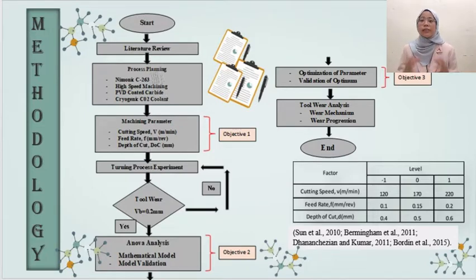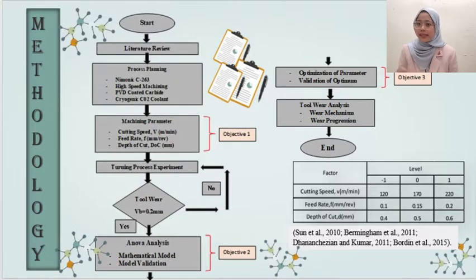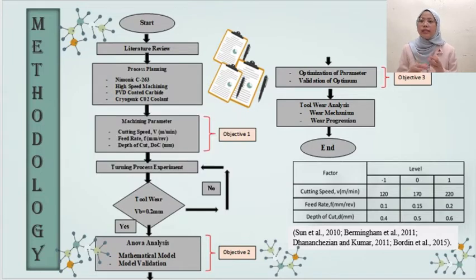Then, the research is planned using Nimonic C-263 with high-speed machining with the help of a PVD coated carbide insert, assisted by the cryogenic CO2 coolant. The cutting parameters like the cutting speed, feed rate, and depth of cut are selected based on the literature review and handbook guidance suitable for the machining process. Then, the process parameters are selected for further optimization using response surface methodology (RSM). The cutting parameters selected in this experiment are based on current and past research.